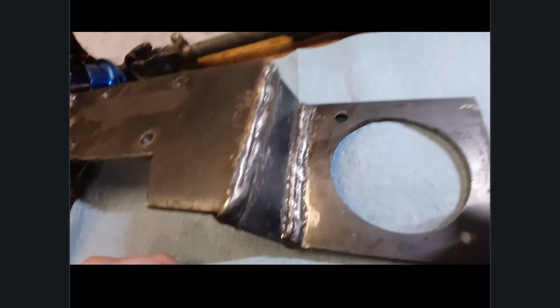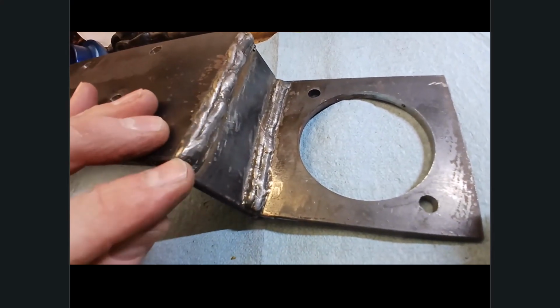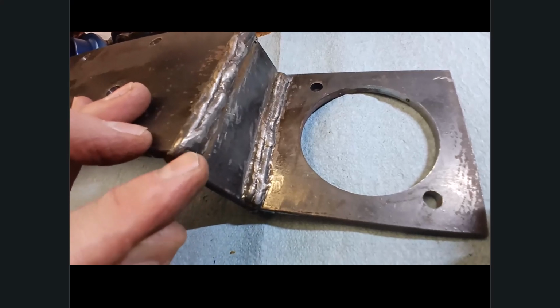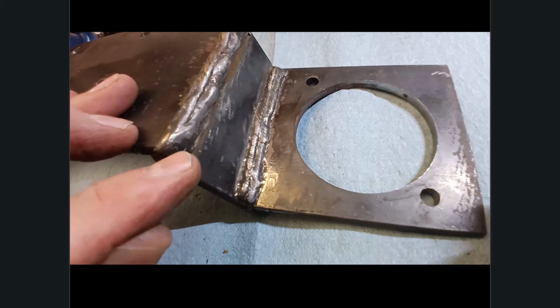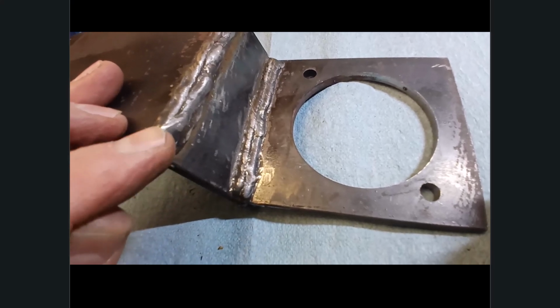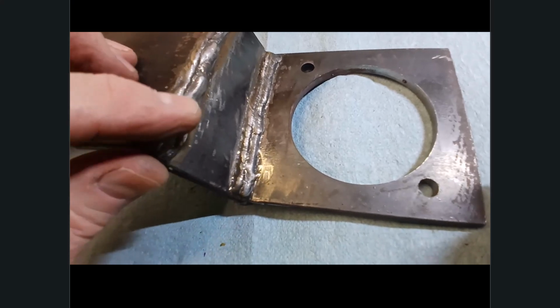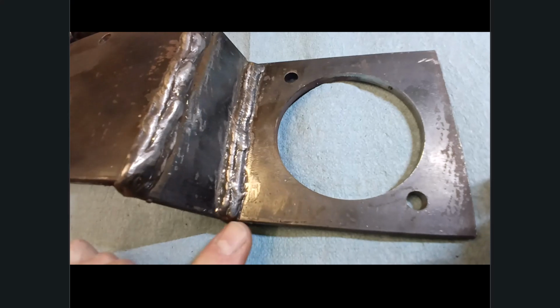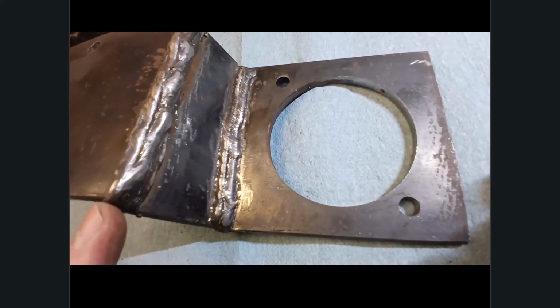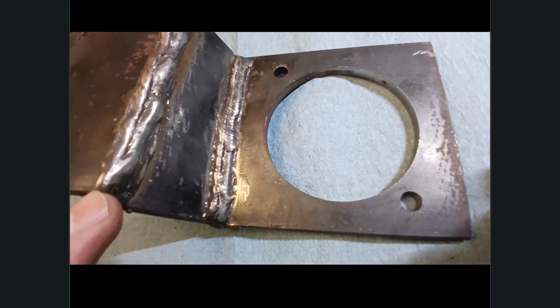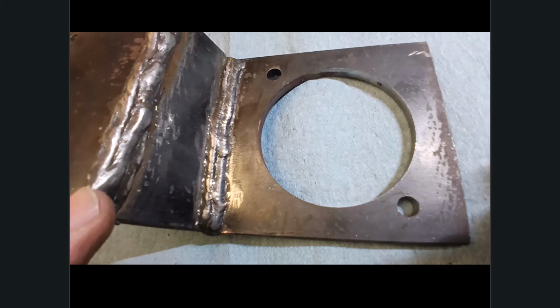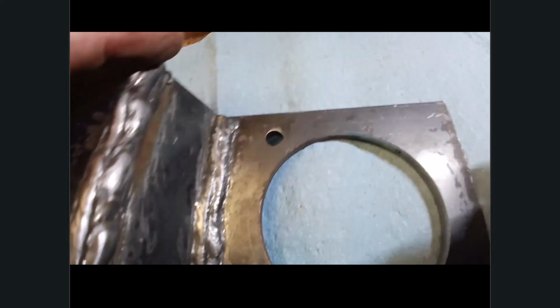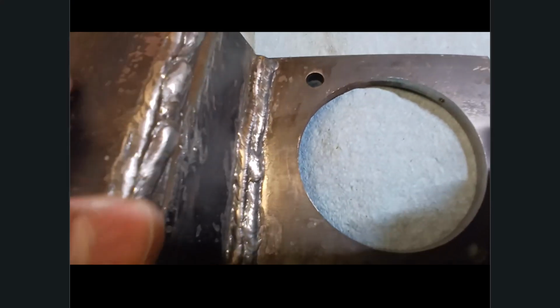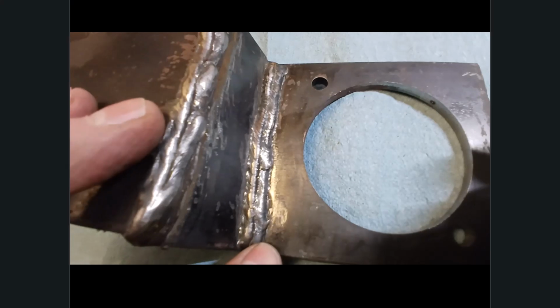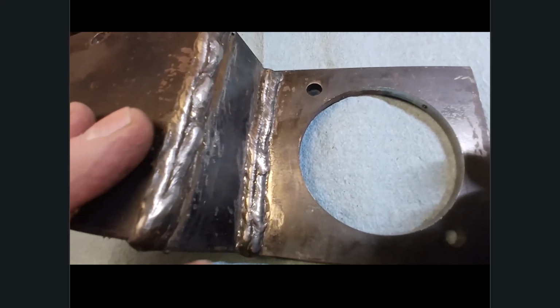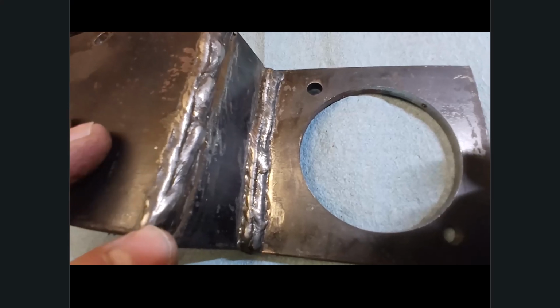Another issue I had to be very careful about when using 7018 rods was that if you start an arc with a greater distance, a wider air gap between the tip of your rod and the surface steel, you'll get porosity. So you have to go through any starts and stops or anywhere on your bead where you see small holes where gases came out because it was too hot. And then you have to grind those off and repair those porosity areas. I only had a couple regions where there were some starts. You commonly don't get them on stops, but you get them on starts if your stick comes up too high. There's too much of an air gap between your stick and the surface steel.